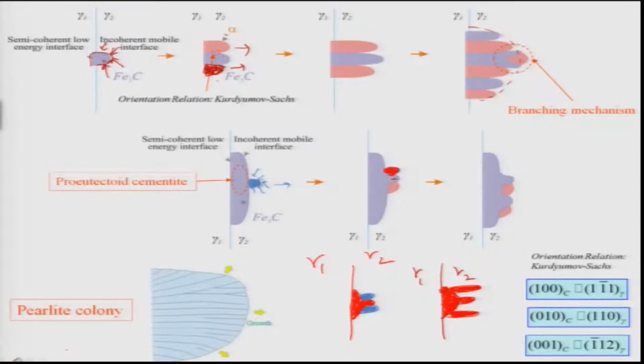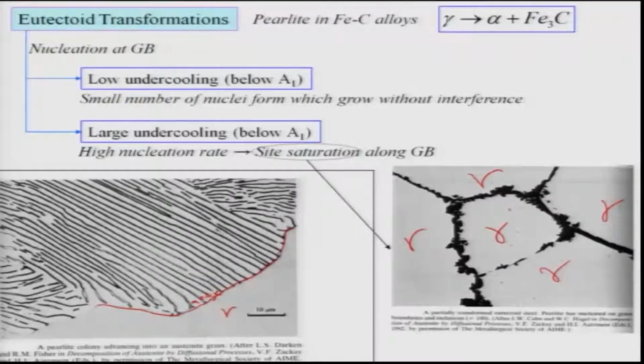So as you see, nucleation is not a very critical step for the formation of pearlites. That is very clear. Nucleation can happen in many ways. It can happen on the pre-existing grain boundaries of gamma, or on the pre-existing pro-eutectoid phases, either pro-eutectoid cementite or pro-eutectoid alpha, and this can lead to formation of these colonies. So either way, whatever the situation, it will lead to formation of these colonies which you have seen in the microstructure.